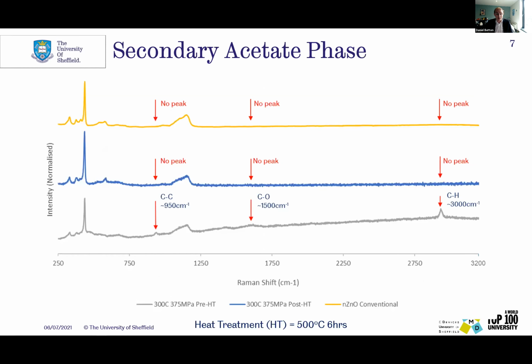This is the sort of thing we need to look at. There have been some things in the literature, because we mix it, I should have mentioned, not just with water, but with acetic acid, so basically vinegar, and understanding the fact that sometimes you can observe a residual acetate phase. In the work that I've been doing, I did notice that after the cold sintering, I needed to do a bit of heat treatment to remove that acetate phase. Other groups have shown that it actually removes itself at 300 degrees. So this comes down to understanding and controlling conditions, and perhaps different equipment setups are very important to understanding this process and optimizing it as best we can.